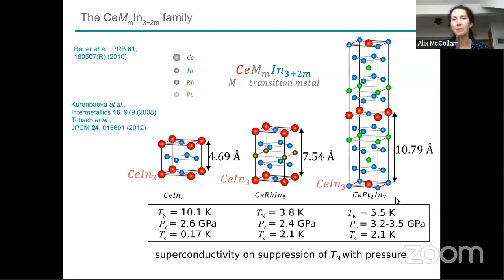I think the measurements under pressure. One thing that would be interesting is to pin down whether the Fermi surface change really coincides with the suppression of the antiferromagnetism or not. So really to measure the quantum oscillations across the transition with pressure in more detail, with better resolution, and up to possibly higher field than have been done. That would be a kind of dream measurement. It would answer a lot of questions.